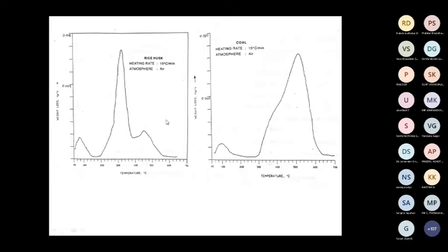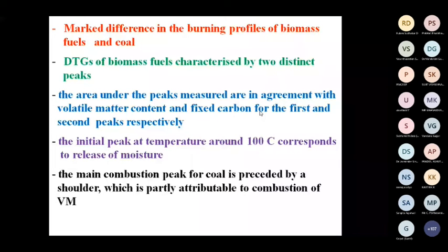Then this for rice husk, second peak. Whereas coal, you have only one peak. Can you now understand? The biomass fuels and coal, same run, same heating rate of 15 degrees per minute, in air. All biomass shows two characteristic peaks, whereas coal has only one peak. So there is a marked difference in the burning profiles of biomass and coal.